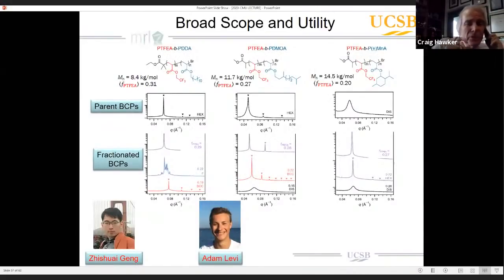But can we actually push it even further? This is some work that Zhishuai and Adam in Chris Bates's group and my group have done recently, pushing the range of different repeat units as well as the molecular weight. I'm not going to go into this in any great detail, but just to say that from the parent block copolymers, which are in many cases either disordered or very poorly defined cylinders, after fractionation, we do actually start to see this very rich morphology for the different samples. Our range of monomer units is also vastly increased.